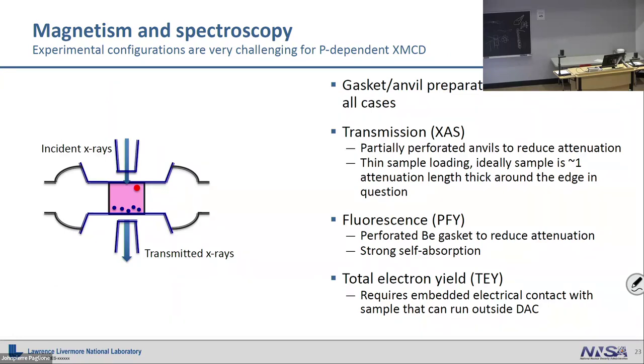So the solution is basically just to drill a big hole through your diamond from the outside so that the diamond, instead of being 3 millimeters thick, is only about 100 microns thick in the center. So the challenge there, of course, is if you make this thing 100 microns and really wide, the diamond is just going to fracture. It's going to break. If you make it really, really narrow, you have to hit it, and you have to hope that your sample is in there too. So there's some choices and some trades you make here.